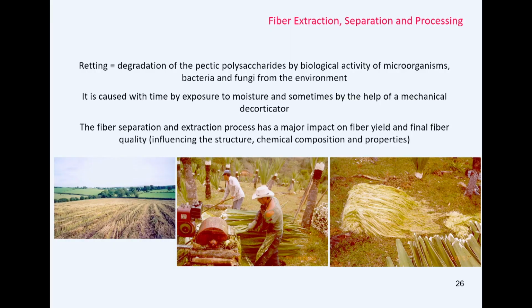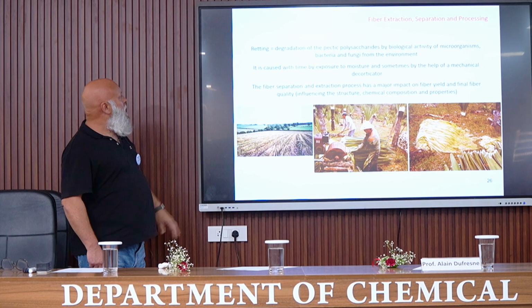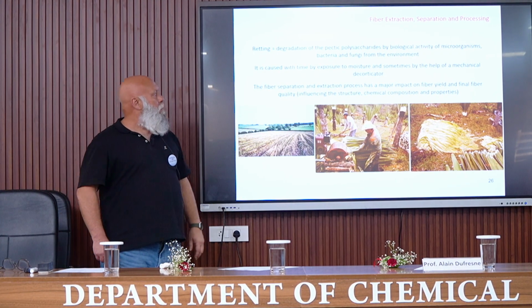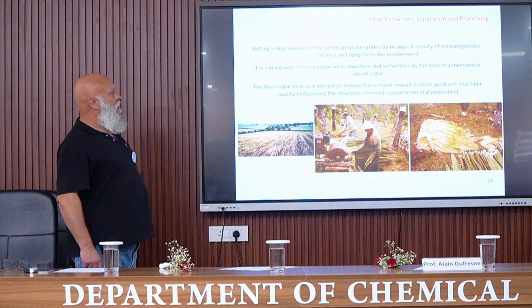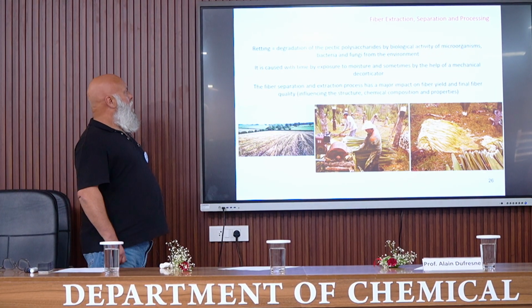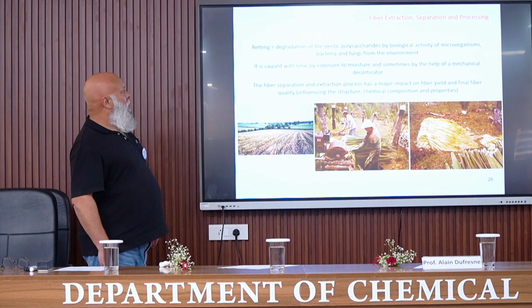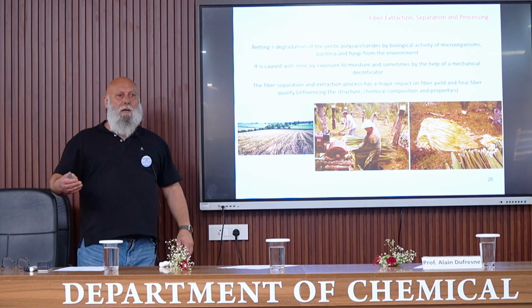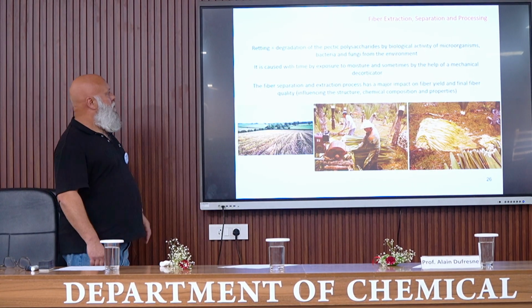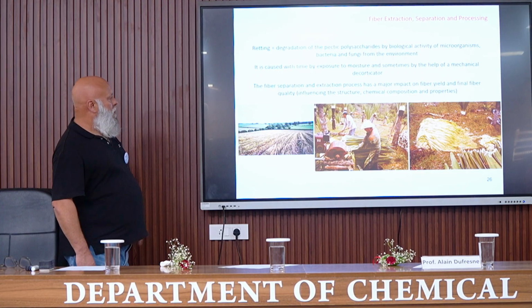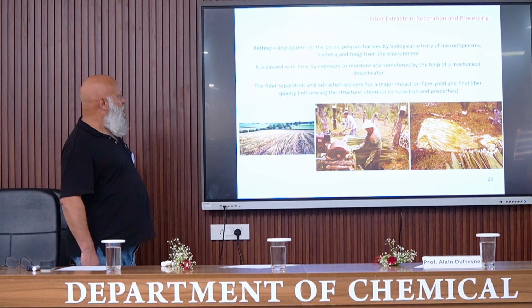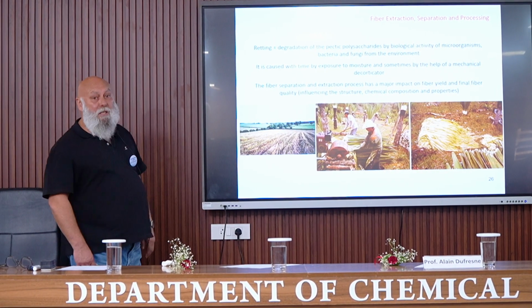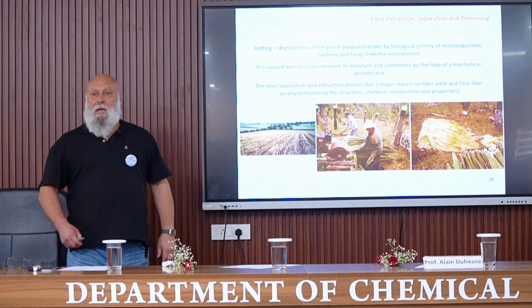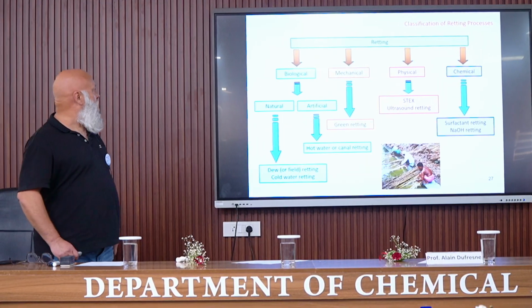So the first step is the extraction of fibers. It's called the separation in the processing, which is also called retting. Retting consists in the degradation of the pectic polysaccharide by biological activity of microorganisms, bacteria and fungi, which are from the environment. So sometimes a mechanical treatment is added to help the separation of the fiber bundles. And so you can see here this mechanical separation process. And of course, this extraction process also impacts the mechanical properties and other properties of natural fibers.